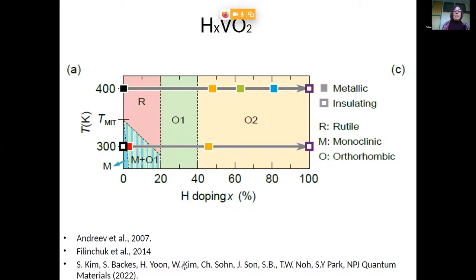And so the first one is a hydrogen-doped version of vanadium dioxide. Indeed, you can insert hydrogen in the pristine VO2 compound, which is here. So this is really the phase diagram as a function of the hydrogen composition in HxVO2, going all the way until 1 H per vanadium. So here you have HVO2, and as a function of temperature.